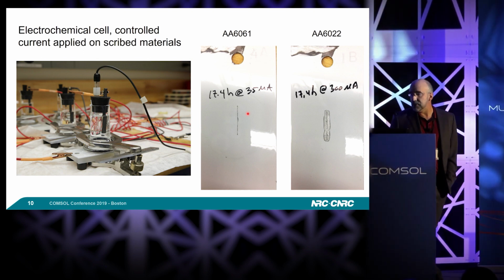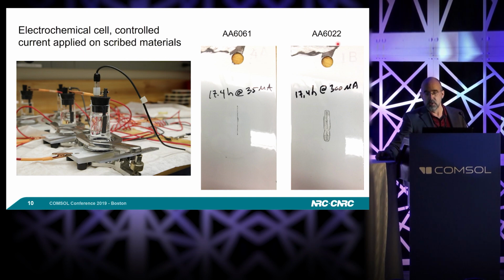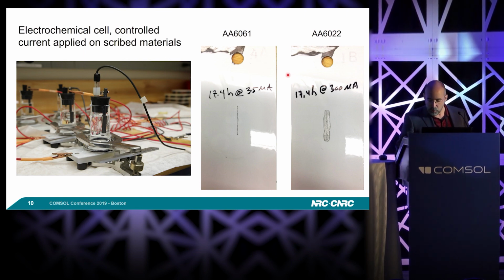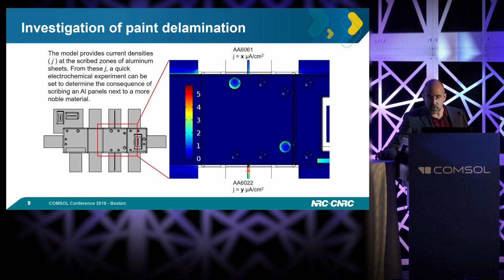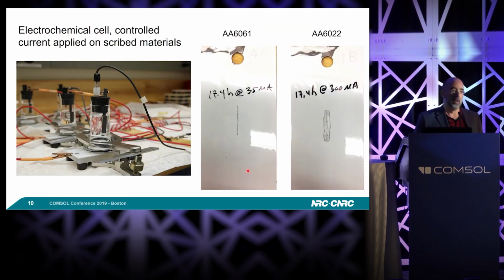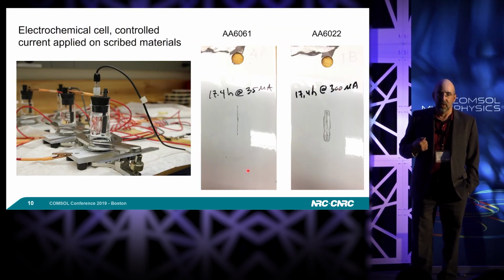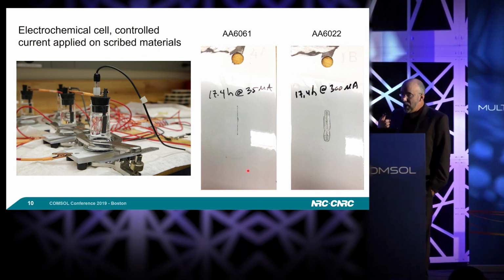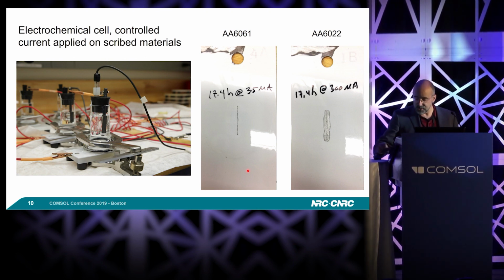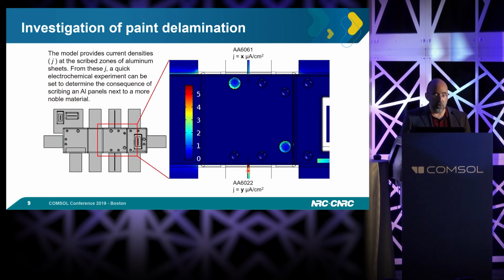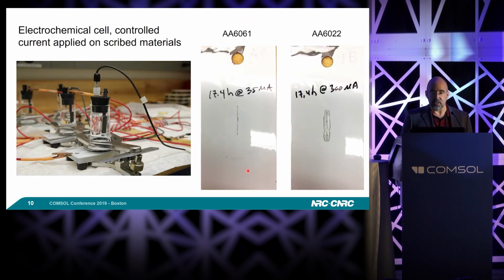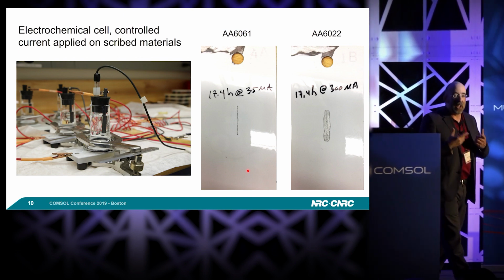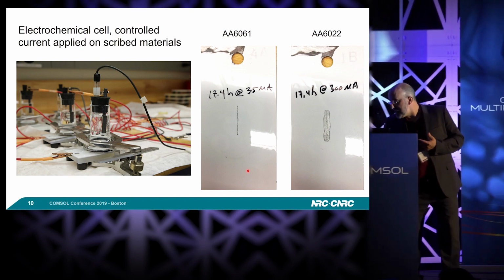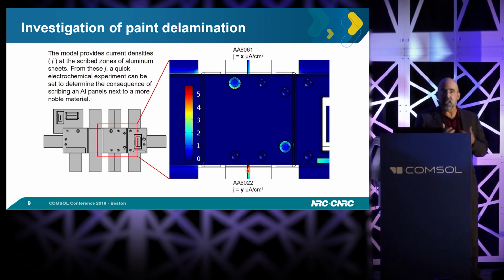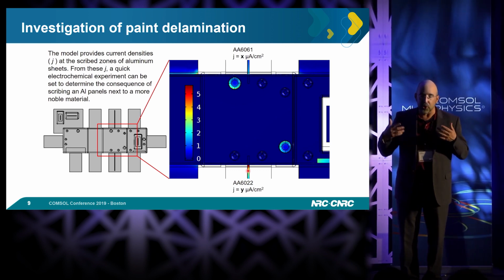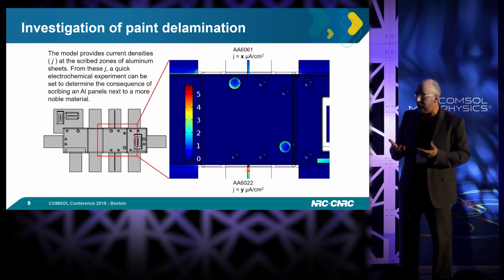What we found is that for the 6022 material, the one that was located here, we were able to peel the paint. So what we can figure out is that this damage here, according to the model, should generate some paint disbonding. But here, we've applied the current. Previously, what you've seen in that case, everything is developed naturally. This is galvanic corrosion. The current is generated by itself.